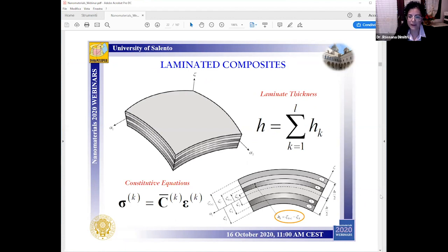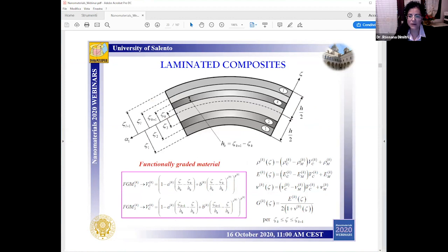laminae within the laminate. And among the class of laminated composites, we can also model the so-called functionally graded materials to account for the continuous gradual variation of the mechanical properties of materials from the bottom to the top side of each lamina in order to reduce possible stress concentrations and residual stresses or thermal stresses within the laminates. So this means that the mechanical properties of a functionally graded material refer to those of each constituent, for example, ceramic and metal, together with a volume fraction defined according to some fixed continuous laws, as you can see